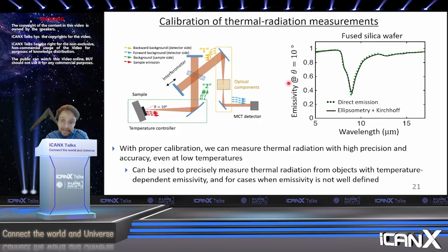Here's the emissivity at an emission angle of 10 degrees, unpolarized, versus wavelength of just a reference sample that we used, which is just a wafer of fused silica, really just a piece of glass. And you can see the direct emission measurement that we do when taking into account all of this calibration that we have to do.